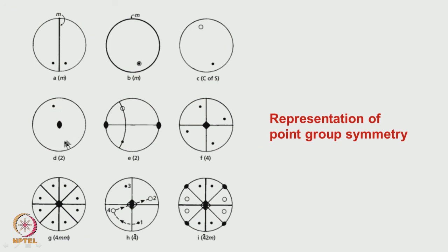These projections, if you look at it, are essentially like a polar projection. So, it is being moved from here, and the same latitudes are concentric circles, it is moved from here to here. This is for 2, where the two-fold rotation axis is lying on this axis. Then when we do a 180 degree rotation, what is on the top hemisphere will go to the bottom, and it will be shown with an open circle. Similarly, a 4-fold rotation, if you consider, will be all on the top circle. This is how it will be rotated.